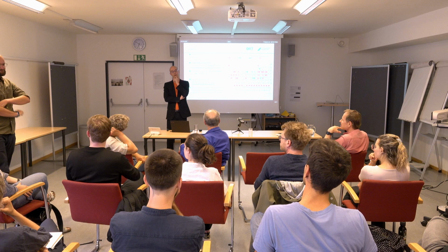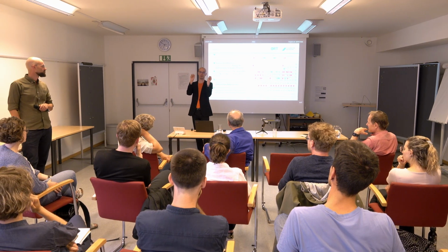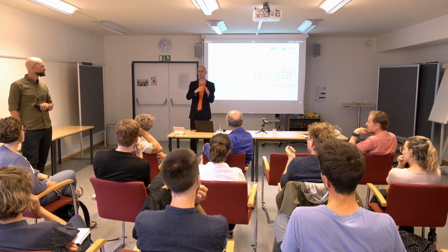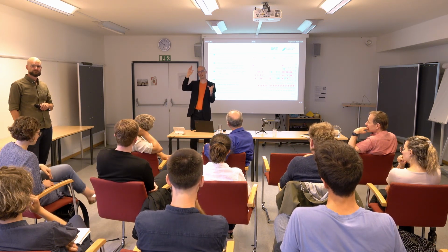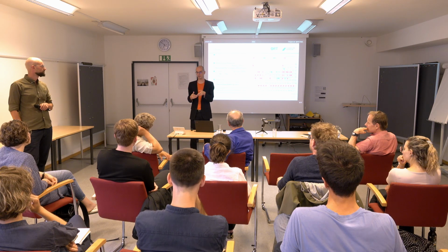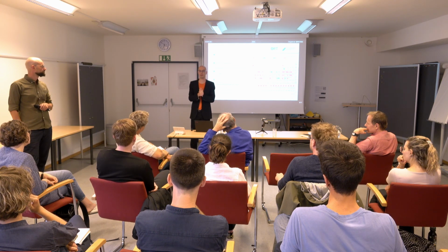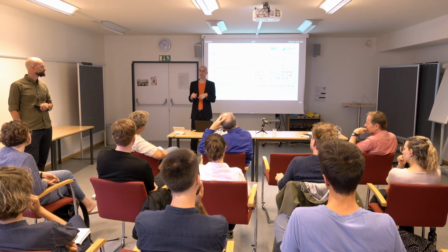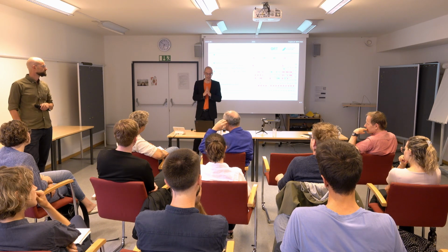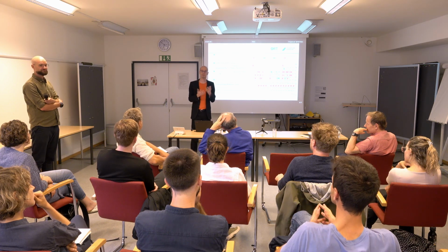Yeah. So, yes, theoretically, there is always an optimal recycling rate, depending on how strongly the environmental impacts, or for example energy requirements, increase the higher the recycling rate you get. So in terms of output circularity, the last 10%, getting from 85% to 95% recycling rate, will require a lot more energy than getting from 5% to 15%, obviously, because you do the easy parts first. For most metals, we're not there. For lead, one could discuss that.